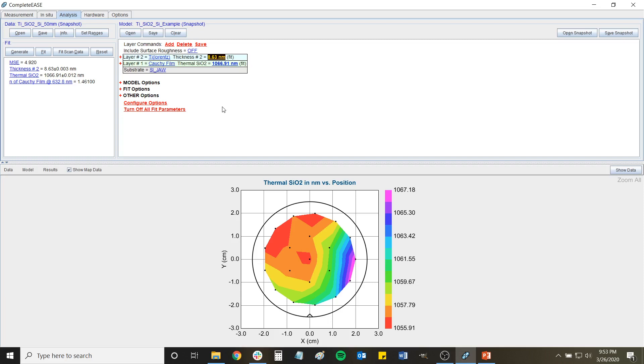Which is you oxidize your wafer or you grow your dielectric, then you do a nice map scan on it and look at the range of thicknesses that you get from it. It should be pretty uniform. And then you use that exact same wafer once you know that, you deposit a thin layer of metal on it, and this can serve you a few purposes.